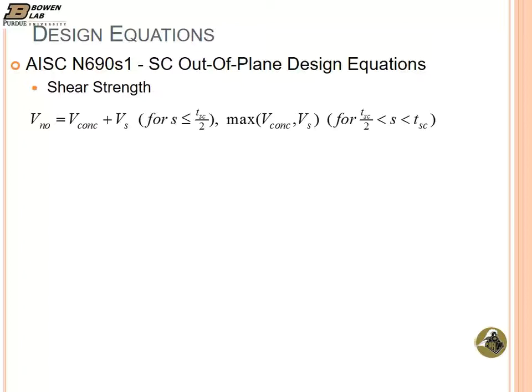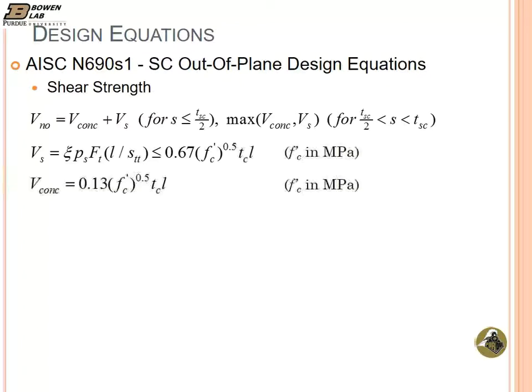But if it's larger than that, then the code allows you to take advantage of the strut and tie effect. So then it becomes the larger of either the compression strut or the steel tie. So by taking that into account, the formulation is modified for spacings larger than T/2. And these are the concrete and steel contribution equations. It's again similar to ACI 349. There are some slight modifications in the numbers. We slightly reduced the concrete contribution due to the size effect in concrete, but the way it's set up is very similar. Again, the steel contribution is either the tie or the concrete compression strut, the larger of the two.